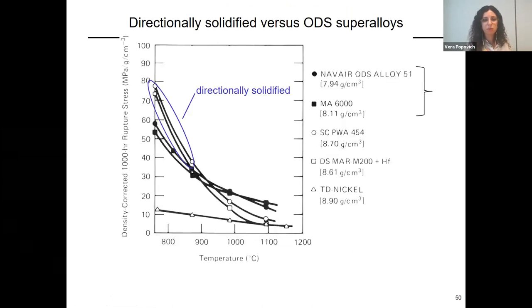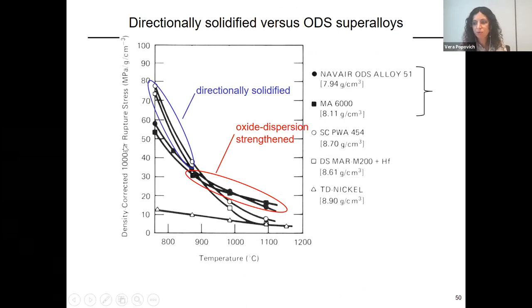An example is shown here. You see an example of the 1000-hour rupture time of alloys. Up to 900 degrees C, you see that the directionally solidified, so conventional, what we saw, single grain directionally solidified alloys, not mechanically alloyed, not oxide dispersion strengthened, are superior. And the reason is because they contain gamma primes, which are the strengthening phase there, up to 900 degrees.